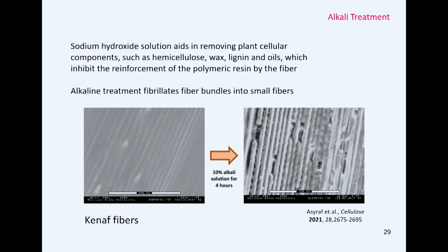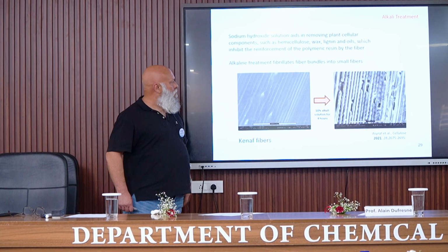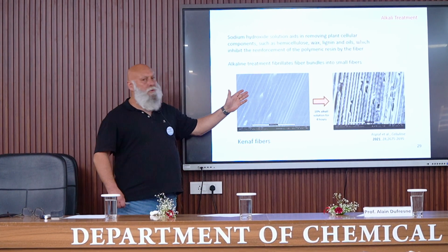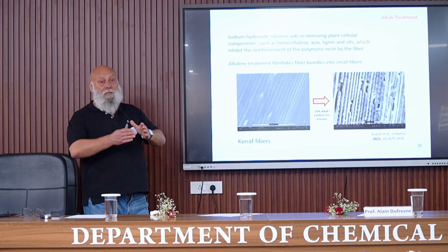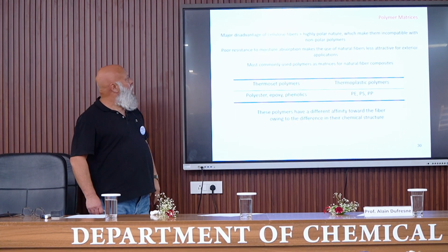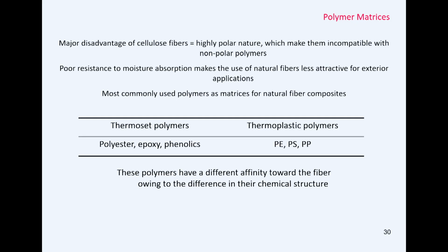So sodium hydroxide can be also used to remove this non-cellulosic material. So this is an example. This is for kenaf fibers of the effect of this alkaline treatment. So it fibrillates the fiber bundles into smaller fibers. So it separates the fibers. So now these natural fibers can be used to process biocomposite using a polymeric matrix.